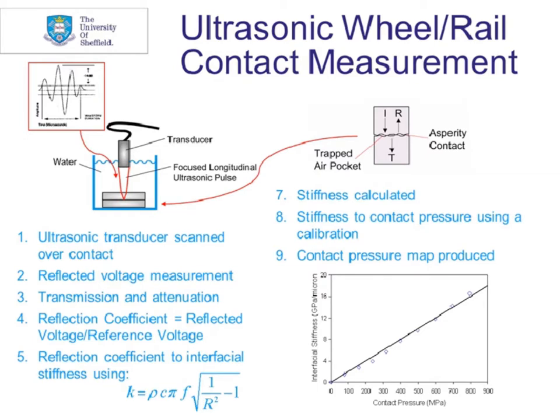At Sheffield, mainly through Rob Dwyer-Joyce's work, we've been developing ultrasonic measurement techniques for looking at machine element contacts, amongst other things. And we used this many years ago to start looking at the wheel-rail interface. So we're able to scan an ultrasonic transducer over an interface. And where you have a rough surface contact, you have little pockets of air trapped. Ultrasound reflects at an air interface. So you can look at the ratio of the reflected voltage that you're pulsing up at the surface and a reference voltage, which you take where you have the bottom part of the interface taken away.